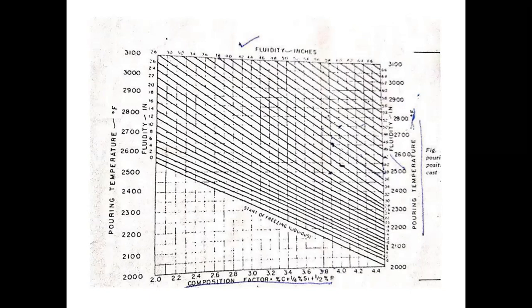And we have to design the gating system considering the last box temperature, 1370 or 1380, whatever we are maintaining in our foundry. As per that only, we have to design the gating system or choke area. If you calculate, just like a student, for the same casting poured at 1350, how much is the choke area, how much is the pouring time? Mind well, if the pouring temperature is 1350 and the same casting is there, the choke area will be more and pouring time will be less. And if you consider 1420 temperature, same casting, pouring time will be more, but choke area will be less. Please calculate. It's interesting, basically.